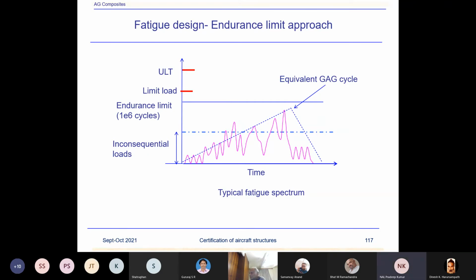Determine the gag damage ratio, as I explained to you. Suppose the gag damage ratio is 0.5. That means one gag cycle is creating about 50% of the damage created by the total fatigue cycles in a flight. So suppose the life for which I want to design the aircraft is 50,000 flights, and 0.5 is the gag damage ratio. That means I need to analyze it for 100,000 cycles.